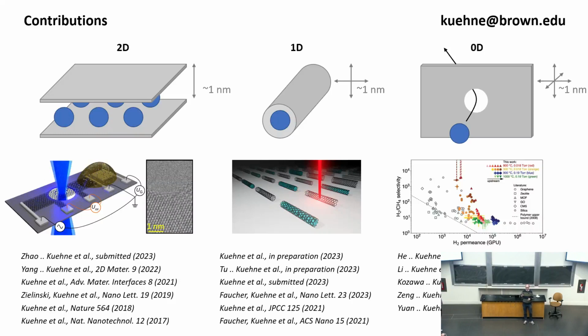So that's actually a challenge, generally. Carbon nanotubes, you make them, but knowing what they are is really difficult. So in our case, we make them, we don't know what they are, we go all the way up to TEM, do diffraction, and then link that to the same position you do your optical spectroscopy. Then see the shift only on the wall you're interested in, then you can say, yeah. So it's a bit involved there, but it's a good question.